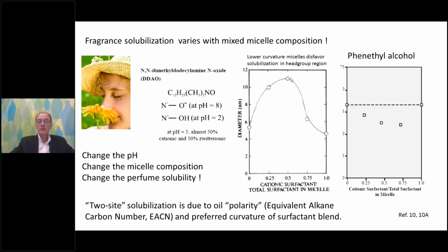Well, when the micelle head groups are crowded together and you have rod-like micelles, that strongly disfavors the solubilization of the phenethyl alcohol. And so we have rod-like micelles that are decreasing the amount of phenethyl alcohol at that particular 0.5 cationic micellar composition. So we change the pH, we actually change the micelle composition and affect our perfume solubility quite a bit.